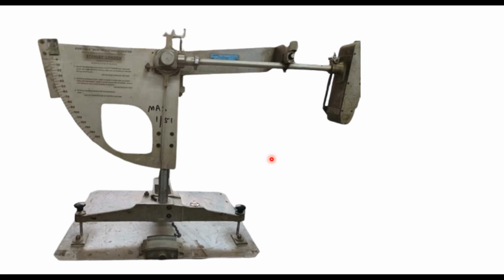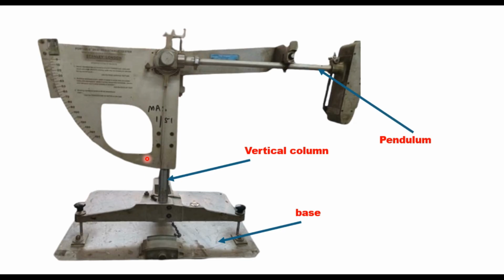A pendulum type friction tester developed by RRL of UK is the most used tester. And this is the pendulum type friction tester. It has a vertical column here, which is fixed to a base, and then a pendulum which can swing about this hinge. At one arm of the pendulum, there is a hinge here to the vertical column, and the second end has a spring-loaded rubber slider, this one, below this. The spring loading is such that a load of 2.25 kg is applied on the rubber slider when it moves over the specimen. A specimen is placed here, and this pendulum can be rested on this horizontal arm, and it can be released by pressing a button here. This button can be pressed to release the arm.